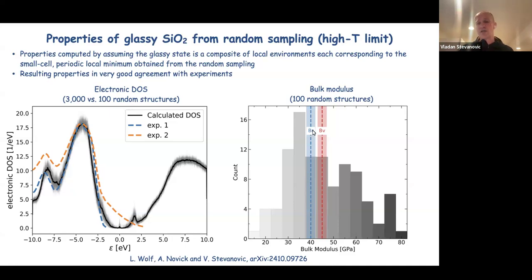two limits for composites. One is called the Reuss and the other one is called the Voigt limit, which we can calculate. We can then use the central limit theorem to estimate error bars on these limits, because we are taking 100 out of 3000. So what you see in blue is the confidence interval, 1 sigma pretty much for the Reuss and 1 sigma for the Voigt. And they are the result that we would call a bulk modulus of a glass.